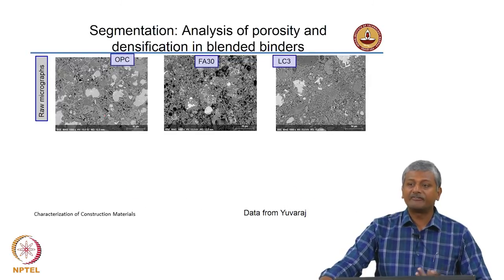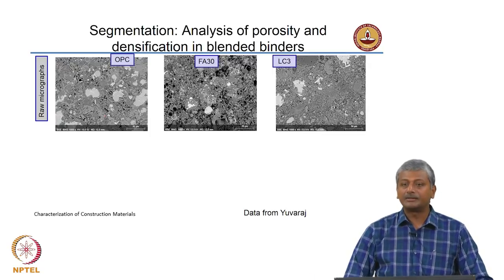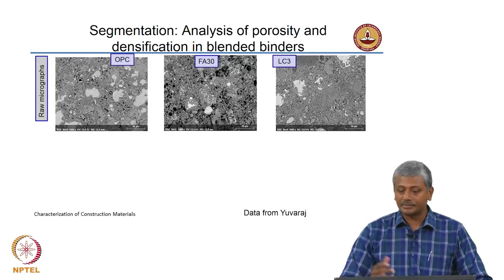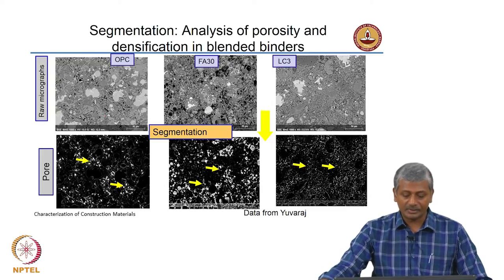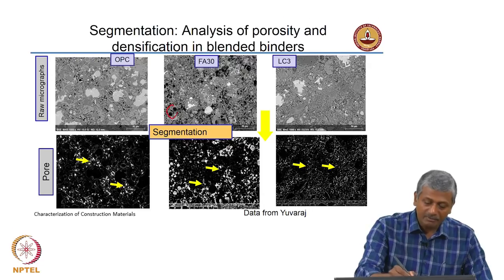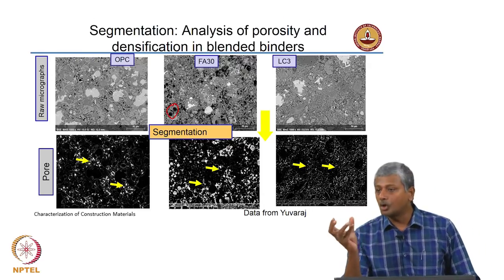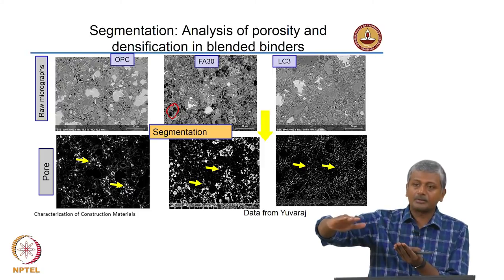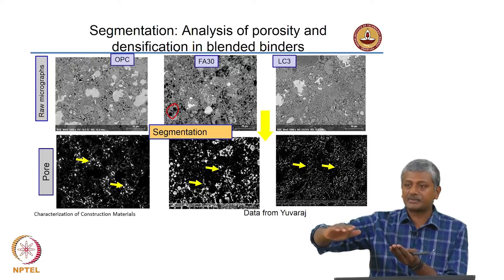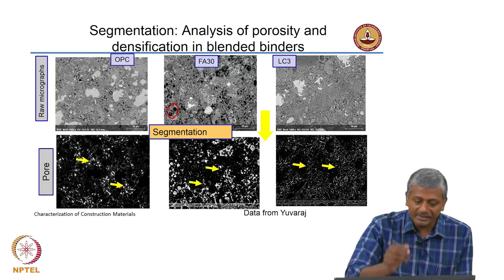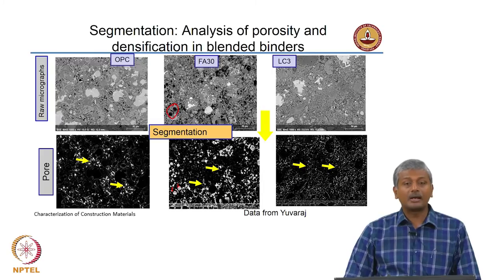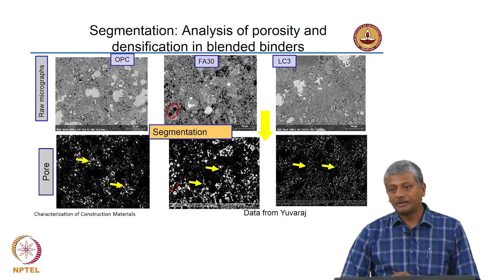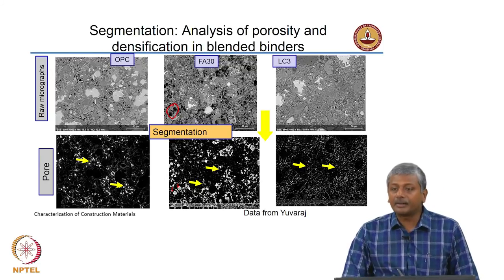This shows effects of different types of binder systems: ordinary Portland cement, fly ash at 30% replacement, and limestone calcined clay system. If you do segmentation you can actually assess the kind of porosity that exists in your systems. Only problem with fly ash is that the fly ash particles, which are hollow spheres, when you prepare your polished sample may appear like porosity when cut across. You need to apply certain kernel filtering operations to fill up those holes and not include those as porosity — for instance, any hole greater than a certain diameter can get filled up and avoided in the porosity calculation.